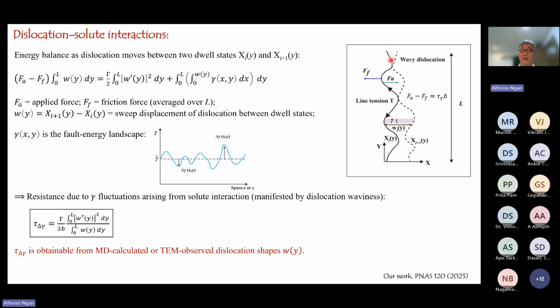So we look at a wavy dislocation like this and look at two dwell states. We look at this shape, and then in the next time instant, the dislocation has migrated to a new shape. So ξ and ξ plus 1 will be the two shape functions of the dislocation, where x is this direction. So we are treating the dislocation as a wave, while x would be the displacement, and y is the variable along the length of the dislocation. Between these two states, we can write down this equation as an energy balance.